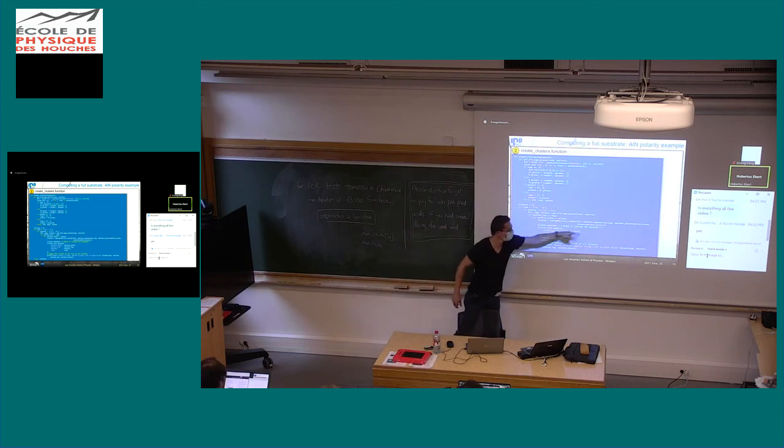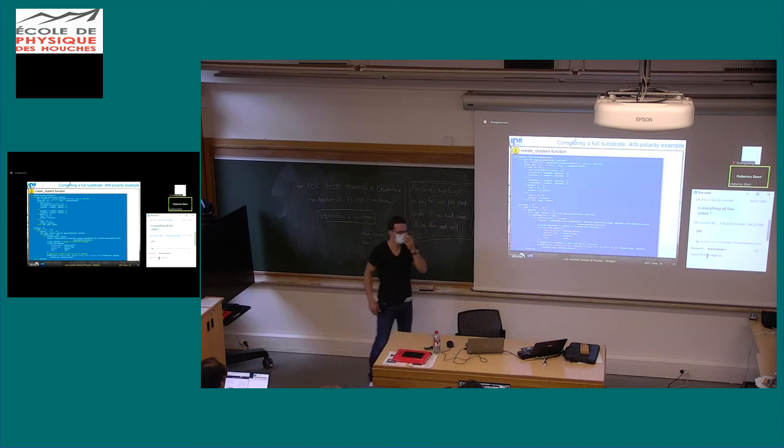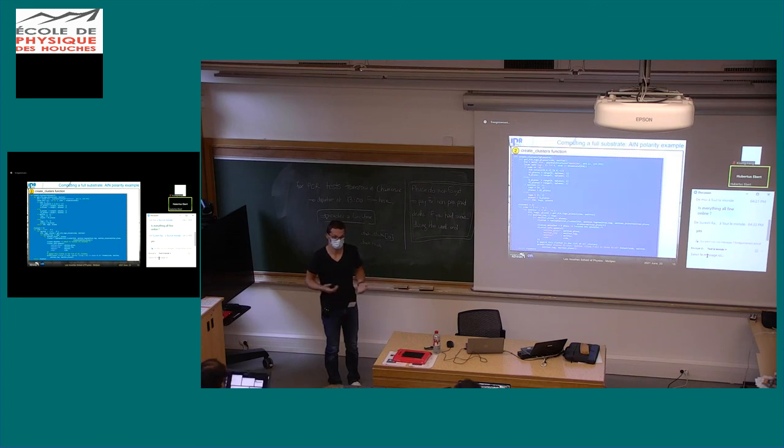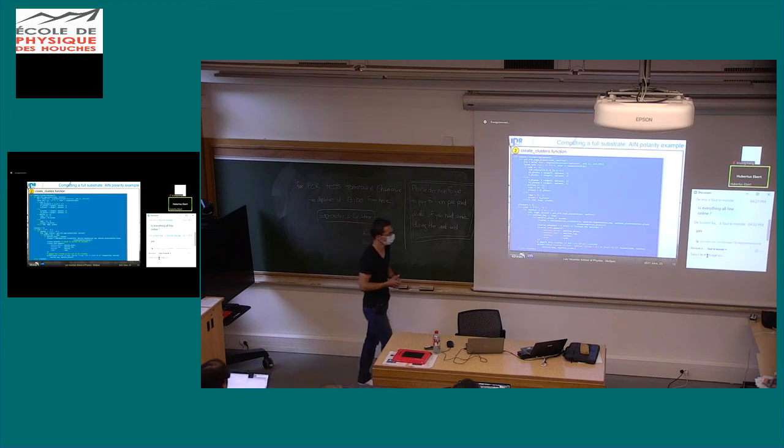So the emitter plane plus 2. It is usually a good idea when you make some photoelectron diffraction to have at least 1 plane below the emitter. Because otherwise you will never see the backscattering components of the last plane that may exist.